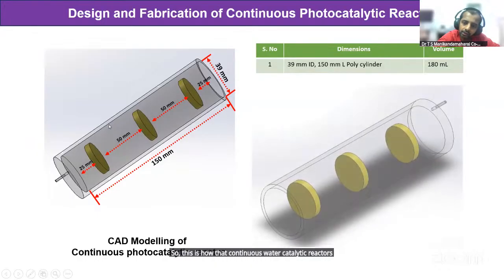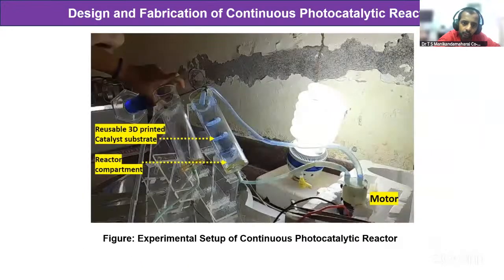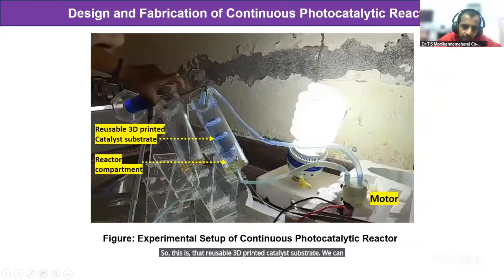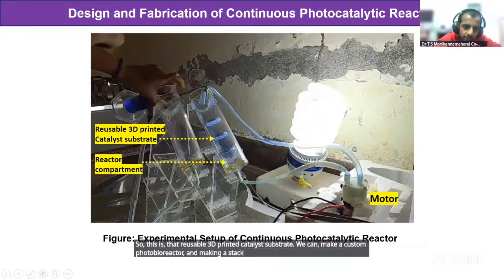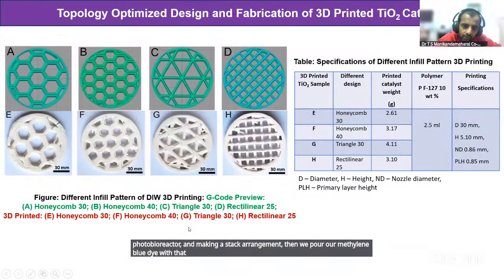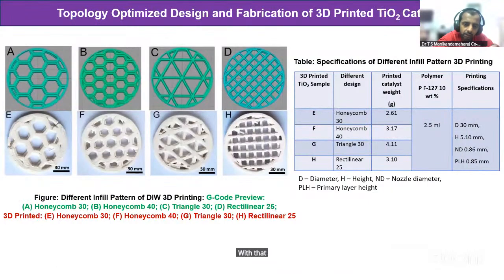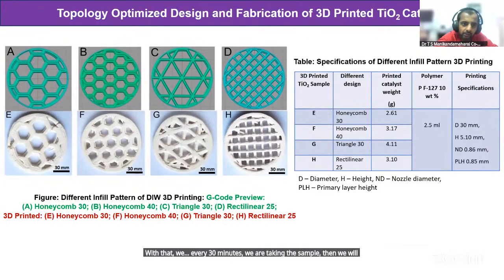This is how we designed and modeled the continuous photocatalytic reactors. This is the reusable 3D printed catalyst substrate. We can make a custom photobioreactor in a stack arrangement. Then we pour in our methylene blue dye under light conditions. Every 30 minutes we take a sample, and then we get our results and discussion.